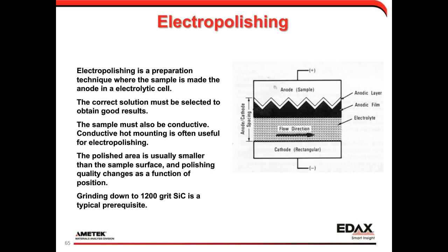It's important to note that the polished area is often smaller than the actual sample surface, and that the polishing quality can change as a function of position. And you still have to do some initial polishing down to, say, 1200 grit silicon carbide as an initial step. And so you can see in the schematic, you have your sample as the anode. You have it applying current and a voltage here with the solution flowing across the material to remove layers of material from the sample surface.